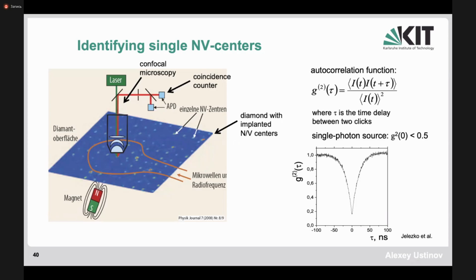It's interesting that if you use optics to detect or to observe some small objects, of course, you are limited by the diffraction limit of the microscope. You cannot really do it better than the wavelength. But once you have a single photon source of sufficiently high intensity, then of course this single photon source, while its size actually is an angstrom size, will nevertheless allow you to observe these individual defects, and you can recognize them as single photon source by measuring this autocorrelation function. That's really kind of beautiful technique showing the individual atomic systems emitting light.